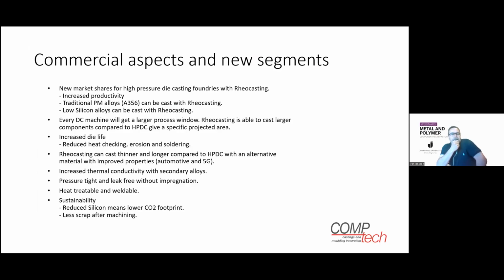And then we have the commercial aspect and the new segments. We see that we bring new market shares for high pressure die casting foundries by introducing Rheocasting with increased productivity. We can use already traditional permanent mold alloys like A356 with Rheocasting, and we can also introduce very low silicon alloys that can be cast with Rheocasting, which introduces new business opportunities. Each die casting machine will also get a larger process window, meaning that each die casting machine is applicable for more part numbers compared to liquid casting.